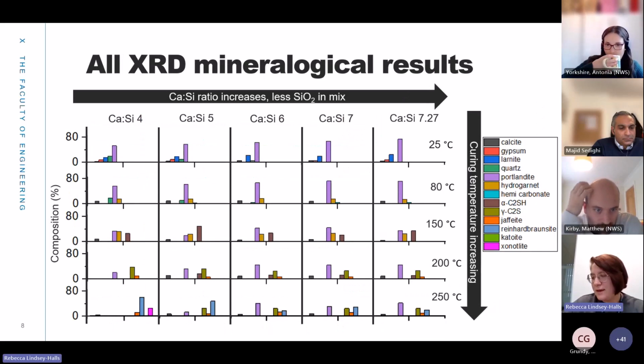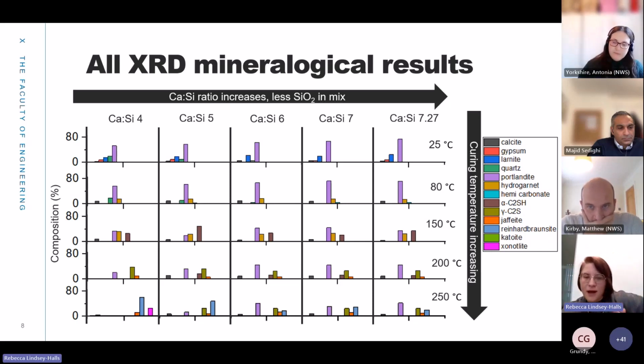So here are all of the results with the mixes made without calcite. These were made again from a calcium silica ratio of 4 all the way up to NRVB, which is 7.27. These were also cured at 25, 80, 150, 200, and 250 degrees. These temperatures were chosen based on existing mineralogical diagrams that show that at these temperature steps, you do get quite different mineralogies forming. And this was just to see if that still applies at these higher amounts of calcium oxide.